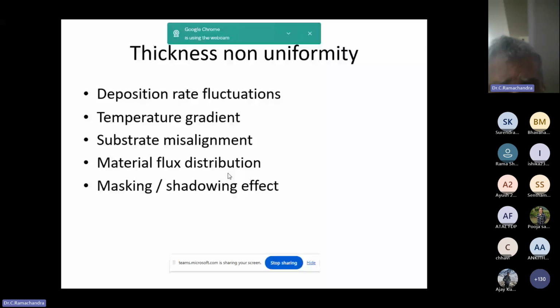There are so many factors which affect this. One is that the deposition rate itself will be fluctuating. The temperature gradient will be there at the substrate. Though you set some temperature, there will be variation. Substrate misalignment is another. The material flux also will have some distribution, that means the density of the particles coming from the target is not the same everywhere. And there will be some masking and shadowing effects. So there are various factors which we need to optimize to have a thickness non-uniformity better than 5%.